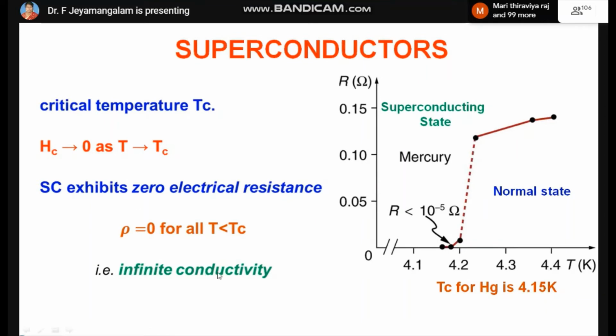And here you have mercury as the superconducting material, because when mercury is cooled, the electrical resistivity drops to 0. Here you are able to see the electrical resistivity drops to 0, and at 4.15 it absolutely comes to 0. So below this 4.15 Kelvin, the material is in the superconducting state, and above that it is in the normal state.